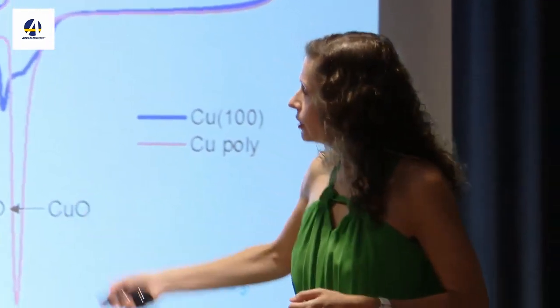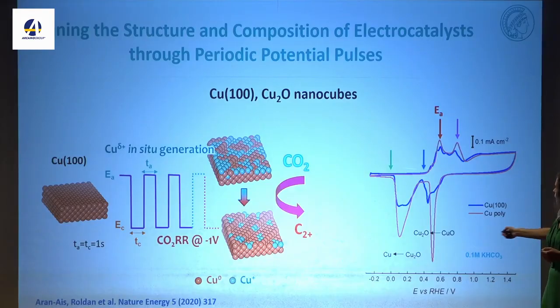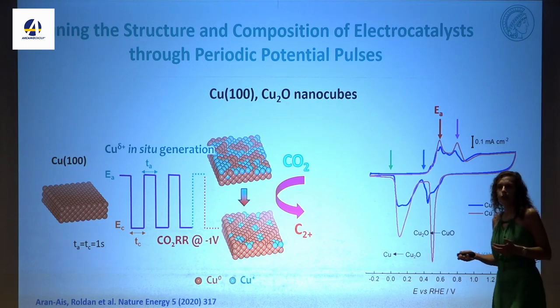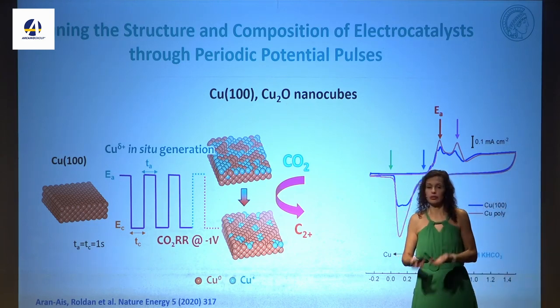Then we say, having oxygen there is good. But if you're working at that very negative applied potential, very easily you can reduce, even if you don't reduce completely. So we try to force the system. So we try to say, we are going to be applying a potential, and we are going to be able to pulse. And by going to anodic potentials where we oxidize the copper, we are going to try to have a mix of metallic copper and copper plus species. This is here the potential where we're doing CO2 electroreduction. And this is here where we are having this mix of metallic copper, copper oxide. So very simple. You just use dynamic reaction conditions.